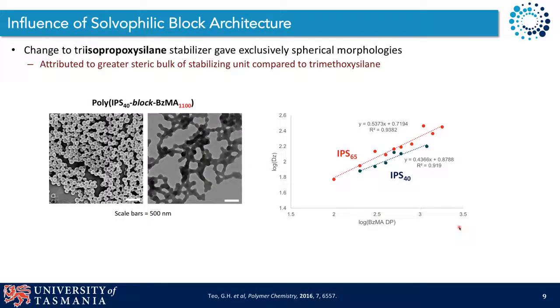Comparing our methoxy results to our isopropyl stabiliser, regardless of the length of our core forming block, we could only form spherical morphologies. That's attributed to the greater steric bulk of our triisopropyl stabiliser compared to the trimethyl version. Across a very wide range, well over 1,000 units of benzyl methacrylate incorporated, we form essentially spherical nanoparticles. Again, we're inhibiting the rearrangement to form higher order structures in that case.